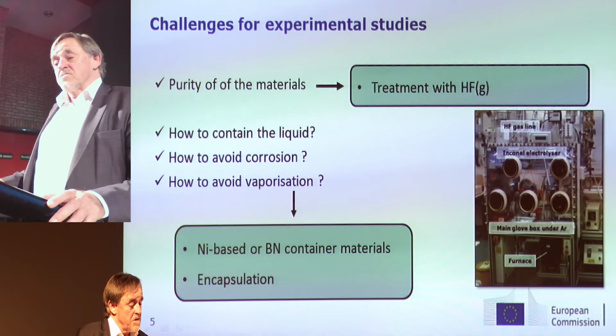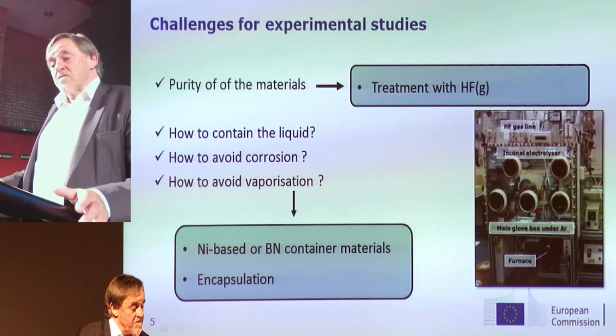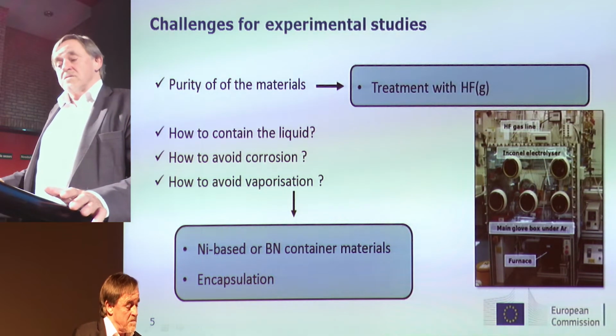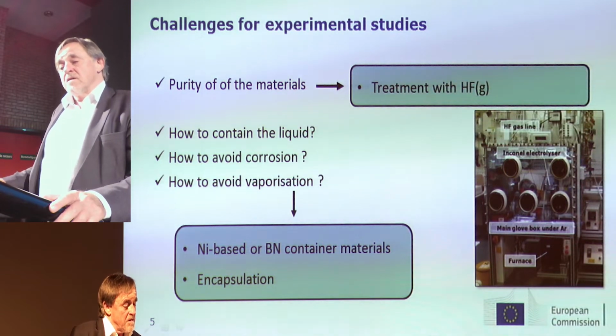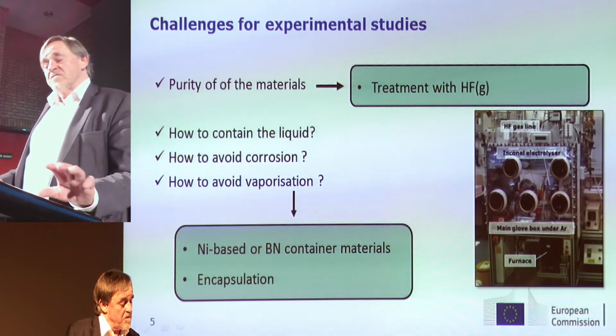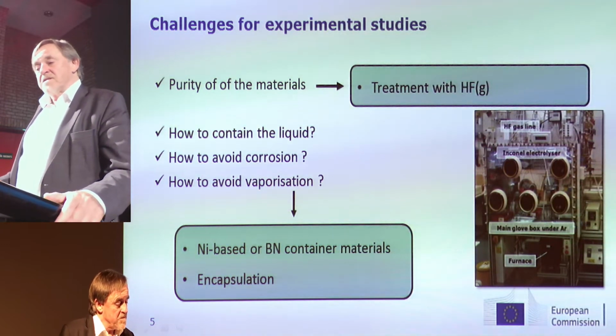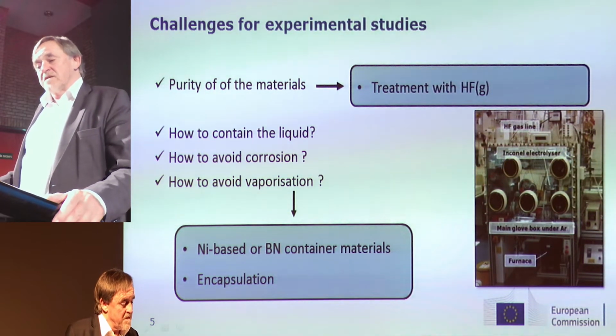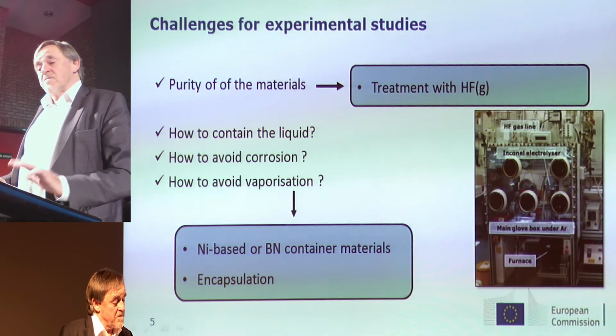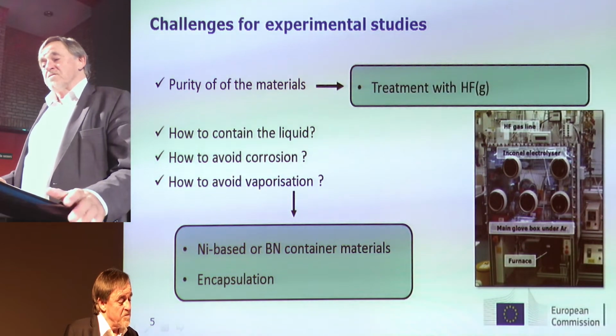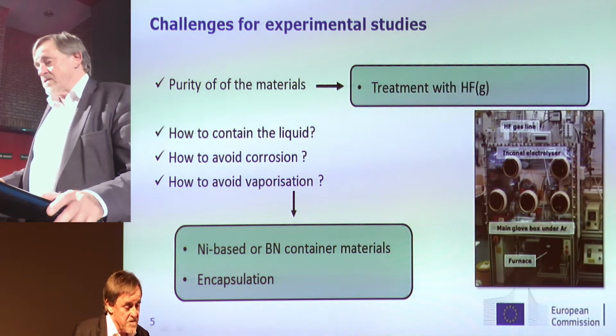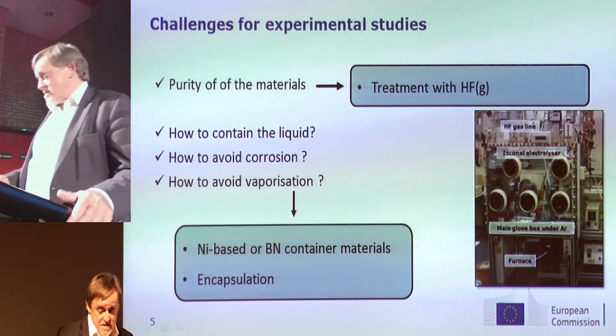We have also, of course, to deal with the container materials to avoid corrosion, to avoid vaporization. So for our activities, we use mainly nickel-based or boron nitride container materials, and we have developed efficient encapsulation to avoid any vaporization or release of material during the tests.